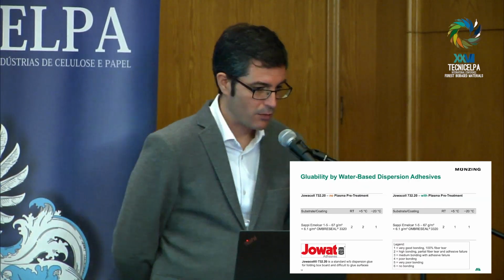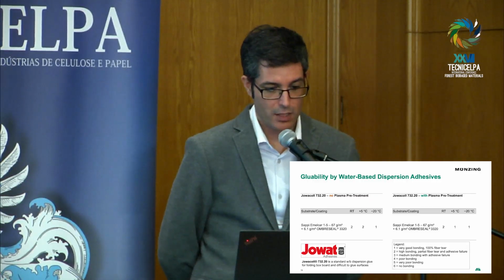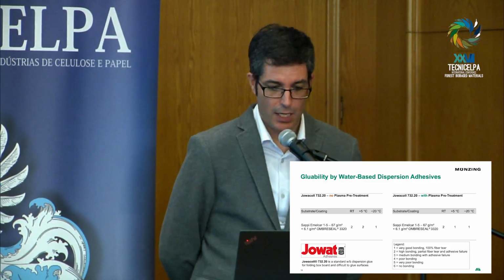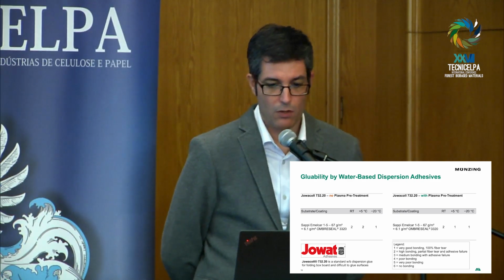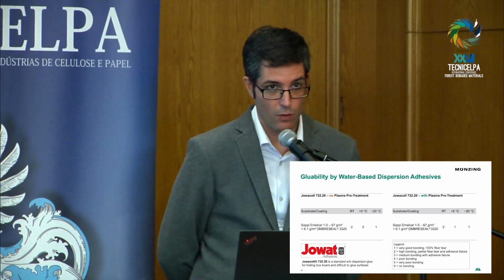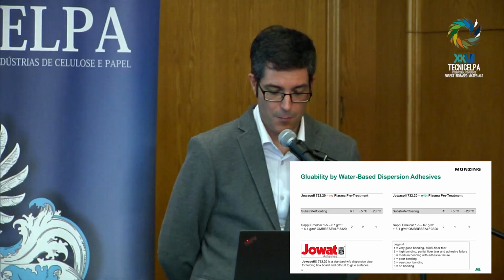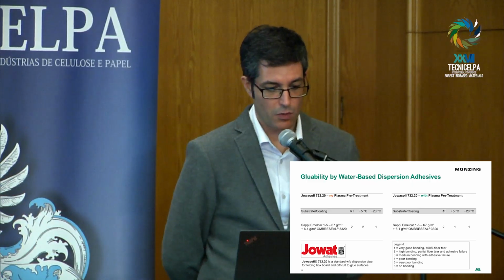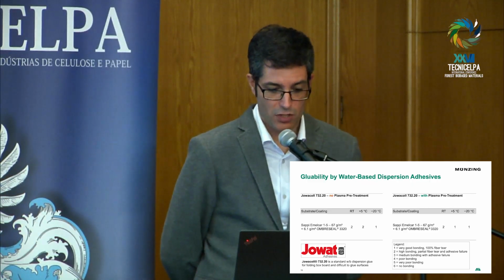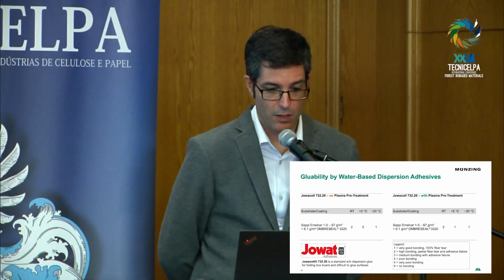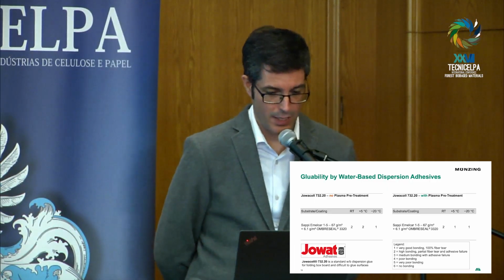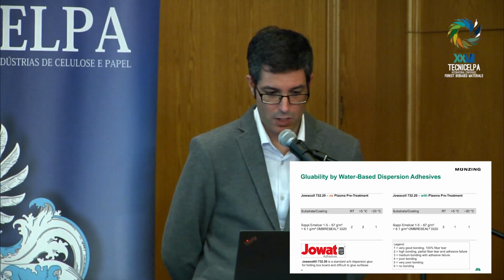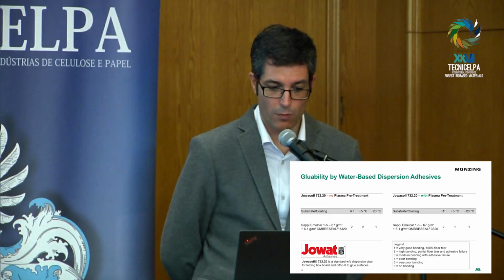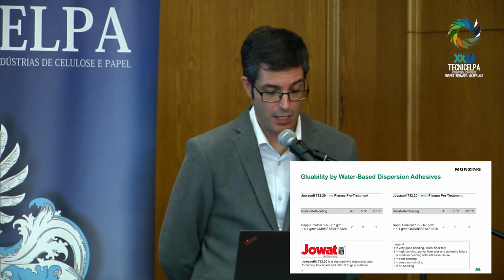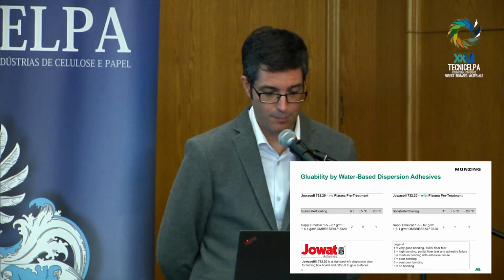Finally, talking about gluability, we know that these water-based materials provide some repellent effect. So it is possible always to use hot melts for gluability purposes. But in that case, we got in contact with Jowat adhesives to also check the suitability of water-based dispersion glues. In that case, the material selected was the Jowat 732.20, which is standard dispersion for folding box board.